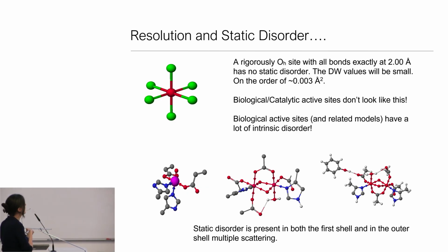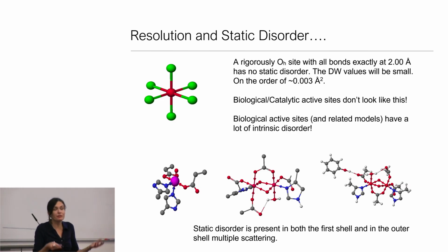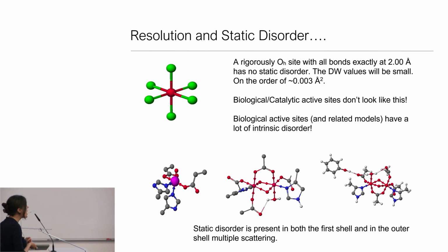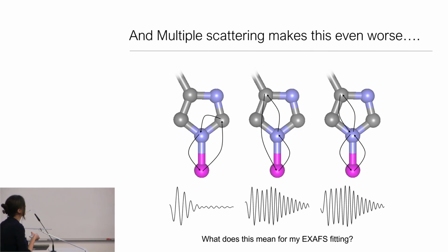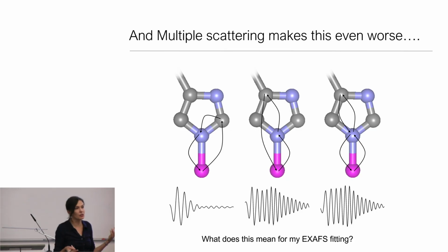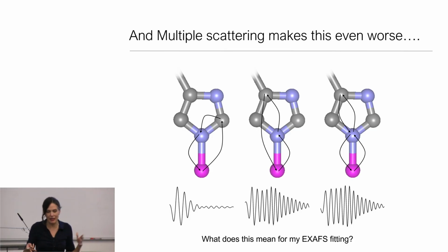But for enzyme active sites or catalytic active sites or basically anything that's a real system, I have these complex active sites that have different types of oxygen, different types of nitrogen, and I can't even separate those. So it all has to get grouped into some average radial distance that in and of itself will also have disorder. On top of that, I also have all of the multiple scattering that can happen. If I just imagine a histidine ring, there are all these different pathways that my photoelectron can scatter, and every single one of those gives me a different type of scattering pattern. This is why in EXAFS in general, we have a real underdetermined problem, right?